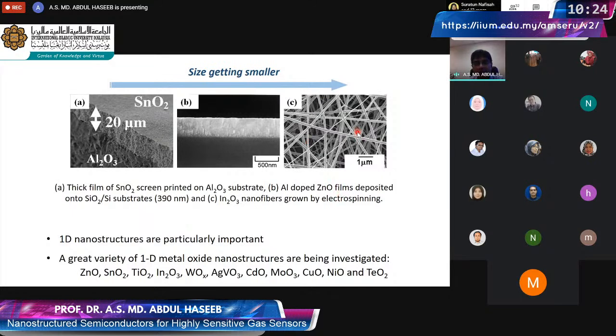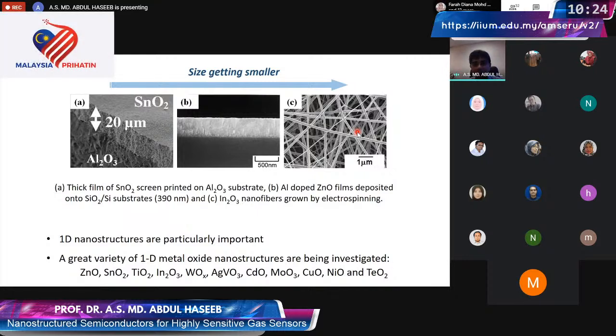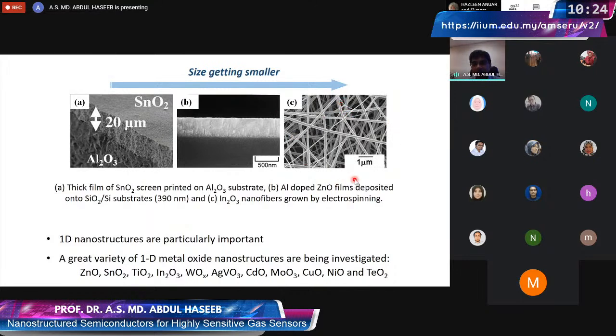And as a result of this, we have many benefits. So one benefit that we have seen is that this dimension is smaller than the dimension of the typical depletion layer. So we have the whole material is active. Number two, in this particular form, you see a lot of porosity. So the gases can diffuse and the whole material system now becomes active. And researchers around the world are now investigating this, particularly this 1D oxide or one-dimensional metal oxides, and all sorts of oxides are being investigated. So zinc oxide, tin oxides are very important material, titanium oxide. We also have indium oxide, tungsten oxide, and so on.